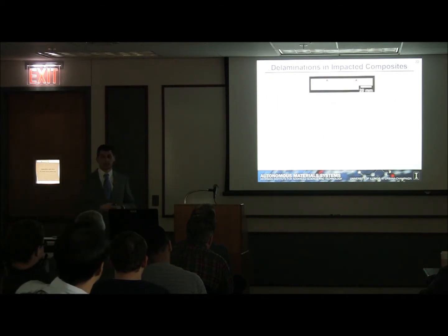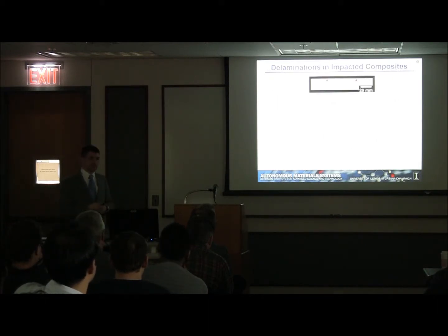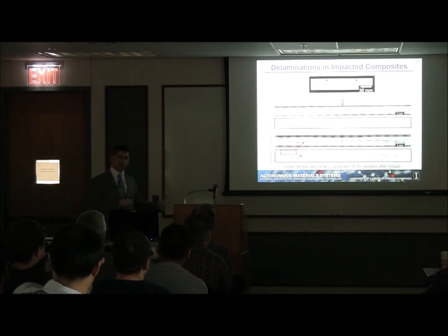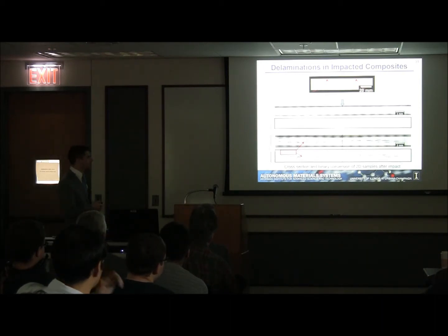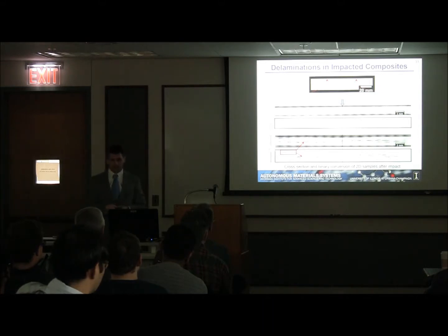And these load drops correspond to the introduction of a very particular type of damage inside of our composites, and that damage is delamination damage. So if we take a look at a cross-section of one of our beams after it's been impacted, and compare one at low impact energies versus one at higher impact energies, we compare a sample with 5 joules, for instance, here. This is the cross-section. This is the corresponding binary conversion of the damage. So we see the cross-section here, no damage present, or very minimal damage present, compared to the 10 joule case where we have this very long delamination between 2 layers, which is, again, sort of amplified by this binary conversion image.